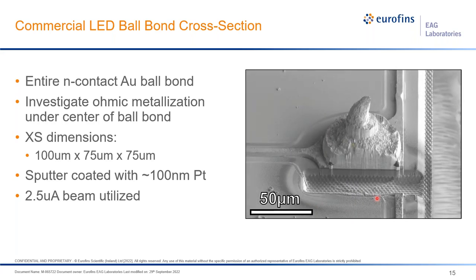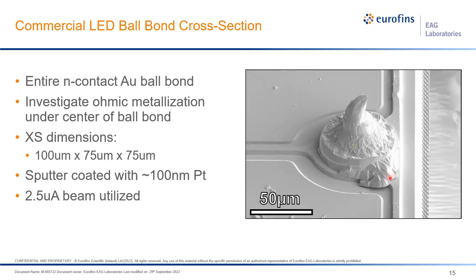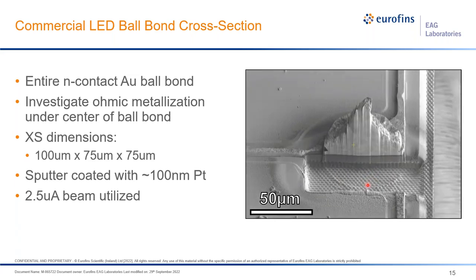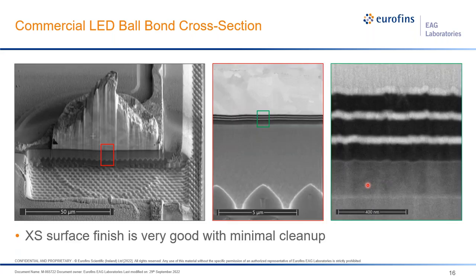So we use a 2.5 microamp beam, and then we do a final cleanup with about 65 nanoamps of just the final cross section. And then this is the kind of information that you could expect from this kind of cross sectioning. So we get a very good understanding of the overview of the entire structure, and then we can zoom in at different features that we're interested in, in this case, looking at the ohmic metal stack here. And then getting even higher resolution, looking at some of these 25 to 50 nanometer thick layers, being able to see some crystallography, their polycrystallinity, et cetera. And then you could even potentially take this further and make a TEM sample from it.